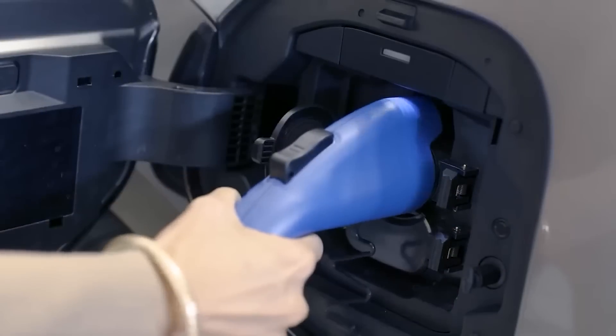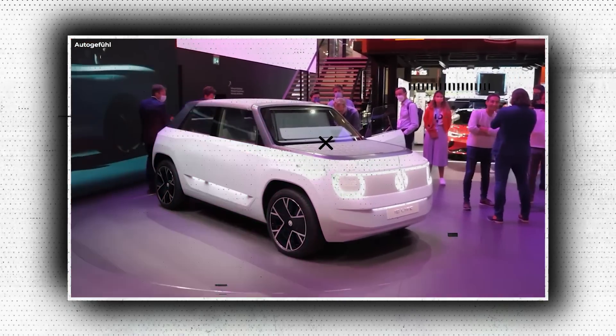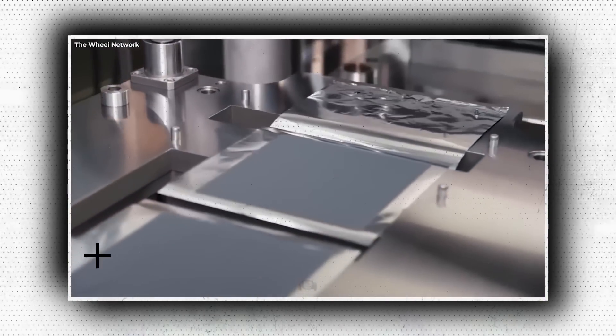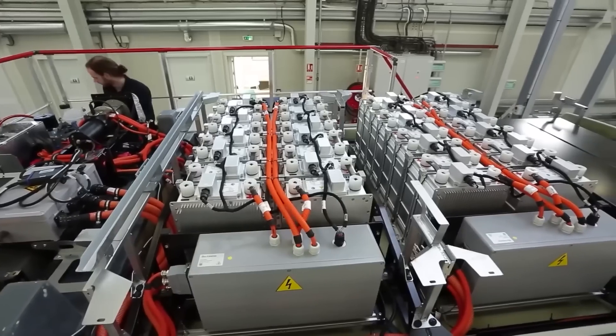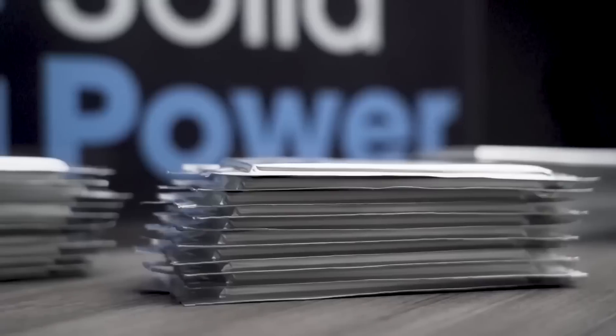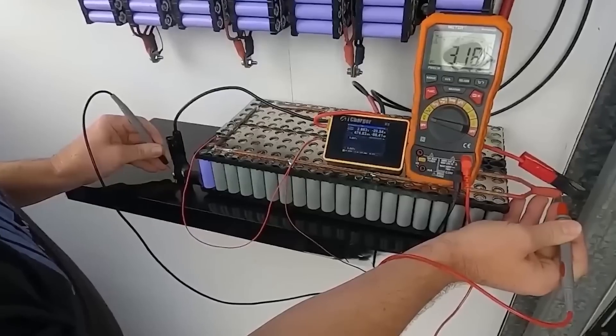Taking things a step further, US-based QuantumScape, in which Volkswagen owns 5%, published a study proving its solid-state battery cells have an energy density of more than 1,000 Wh per liter. It was demonstrated that the batteries could charge to 80% of their capacity in 15 minutes and could retain more than 80% of that capacity after 800 recharge cycles. The key is an anode made of pure lithium metal. The battery won't be ready for manufacturing until 2024 at the earliest.